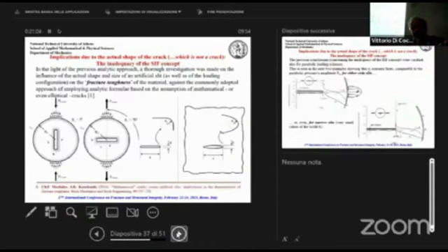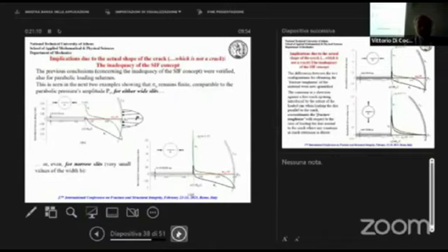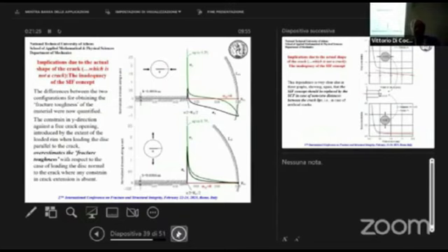So as a next step, we tried to impose the actual load distribution, which is a parabolic distribution of pressure. The results were validated again. The field is bounded. You can see here the limit for the two cases, tension and compression parallel to the crack, which are not identical. There is a huge difference here. And